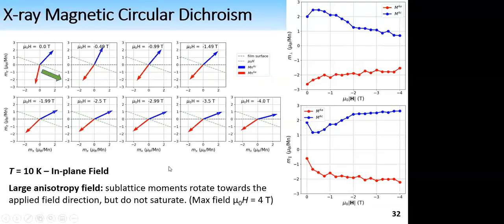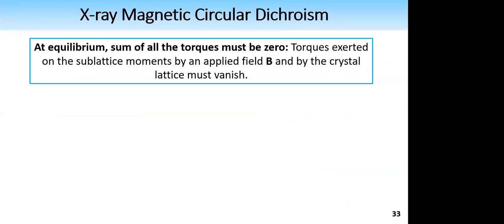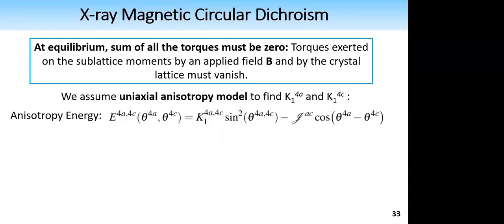In order to actually calculate it, I performed a balancing of torques calculation, which I will show in this slide. We know that at equilibrium, the sum of all the torques must be 0. There are torques due to the external applied field, and also torques due to the anisotropy field. Here I assume the case of uniaxial anisotropy, and hence I can write down the anisotropy energy, which is equal to the anisotropy constant times sine squared of theta minus the intersublattice coupling with the difference of the 2 angles. In order to find the torque, I need to differentiate. So I find the negative derivative of the energy with respect to theta, and that will give me the torques. And then summing all of them.